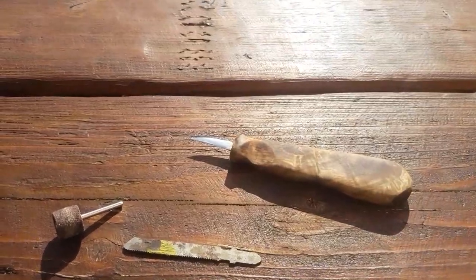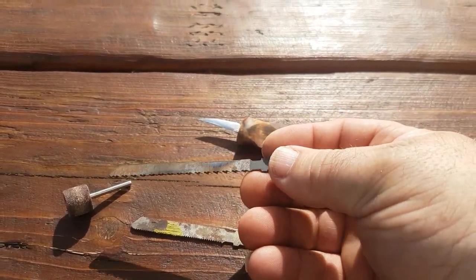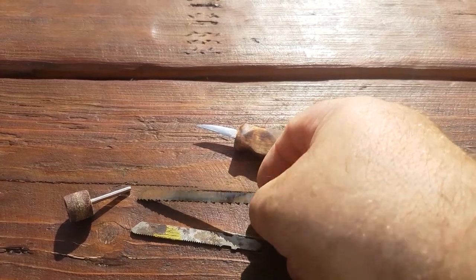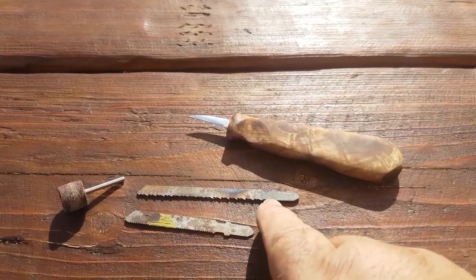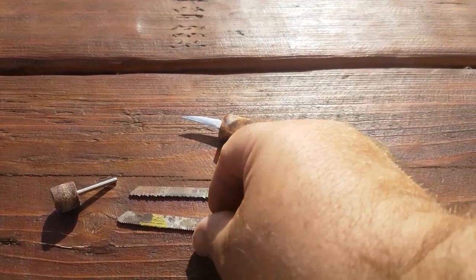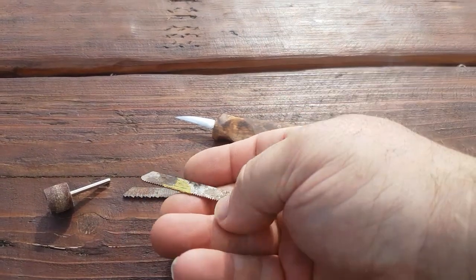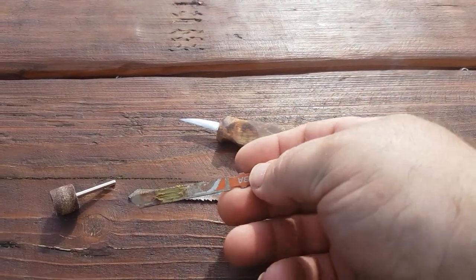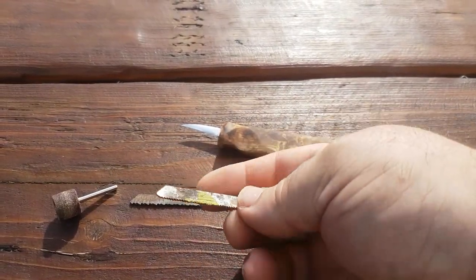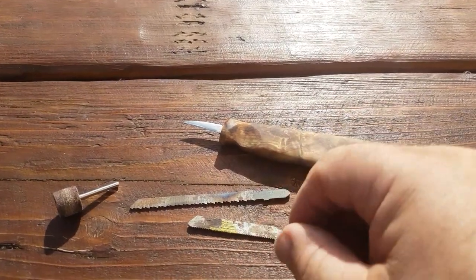There are a few things to watch out for. If the blade has discoloured — I don't know if you can see very well there — but if the blade is discoloured, that's where it's got heated and it's lost its hardness. You can retreat it by sticking it in a flame, getting it up to cherry red, and that sort of thing. But the way I work: you use a hacksaw-type blade, and as long as you keep it fairly cool, you're not going to lose its hardness.